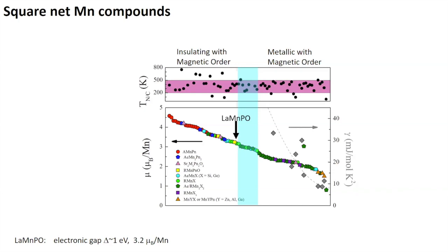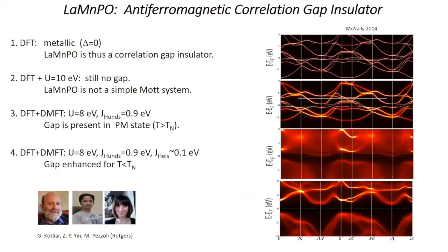It forms in the same structure as lanthanum iron arsenic oxygen. And this material is known to be an antiferromagnetic insulator, has a gap of about 1 electron volt. The experimental gap is about 1 electron volt, and 3.2 Bohr magnetons per manganese. And so it is conveniently located between the transition from antiferromagnetic insulator to an antiferromagnetic metal. So the first step of the handshake, or the validation phase, is then to determine if we could understand the origin of the gap in this material.